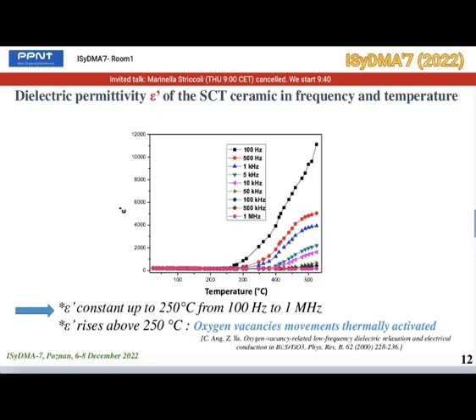Concerning the temperature dependence of the dielectric permittivity of SCT ceramic at different frequencies from 100 Hertz to 1 megahertz, we see that the dielectric permittivity is constant in temperature up to 250 degrees Celsius for all the frequencies, and up to 500 degrees Celsius for 1 megahertz. After that, epsilon prime quickly rises above these temperatures. This may be related to oxygen vacancies that are heat activated in the material.